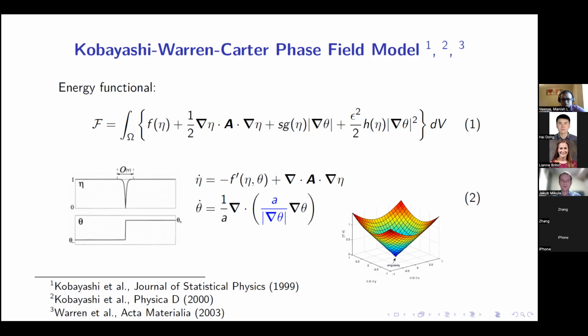We can use phase field models because the advantage here is that we don't have to care too much about the interface. We don't have to explicitly track the interface, as is done in sharp interface models, but all of that information will come out naturally from the phase field model: nucleation, annihilation of the interface, growth and interaction of interfaces.